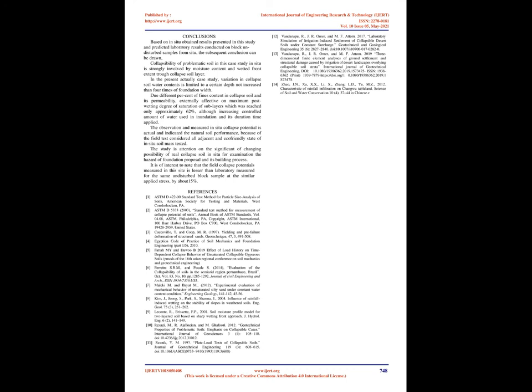Collapsibility of problematic soil in this case study in situ is strongly influenced by moisture content and wetted front extent through the collapsible soil layer. In the present case study, variation in collapsible soil water contents is limited to a certain depth not more than 4 times the foundation width. Different percentages of fines content in the collapsible soil and its permeability strongly affect the maximum post-wetting degree of saturation of sublayers, which reached only approximately 62%, although the controlled amount of water used in inundation and its duration were increased.